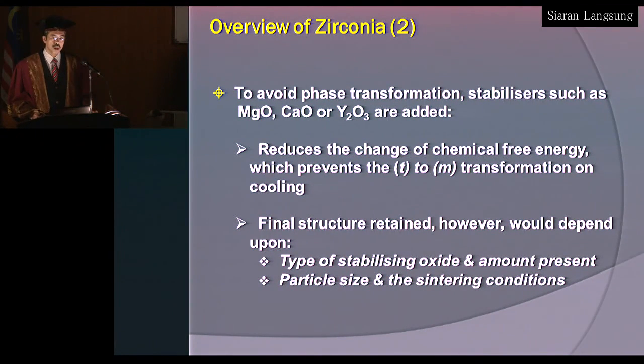Now, what happens when these stabilizers are added? It actually changes the chemical free energy. I will not go into the science behind the transformation, but basically it changes the chemical free energy, which prevents the tetragonal to monoclinic transformation on cooling. And thus, it is possible to retain at least the tetragonal form or the cubic form at room temperature. And this final structure would depend on the type of stabilizers being used, the particle size, and the sintering condition.